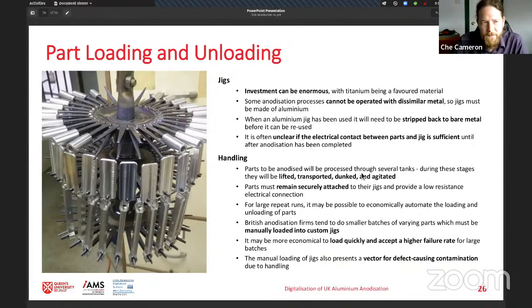So the defects are obviously if you're running the process, the part loading and unloading. When we think about that, it's a big important part because of the need for this to be an electrical circuit. So the jigs themselves, titanium is the favored material for them, and the investment in them can be enormous. It can be very, very expensive. However, that aside, there are some processes that can't be run with a dissimilar metal. So you have to use an aluminium jig. And when you're using these aluminium jigs, every time after you use it, you need to strip it back again before it can be reused.